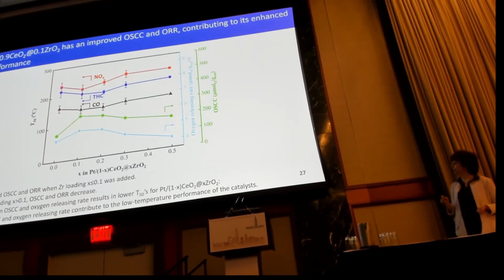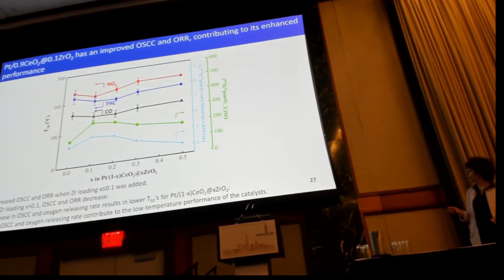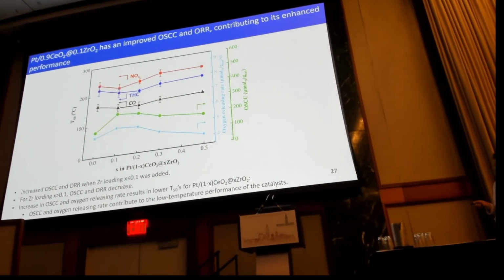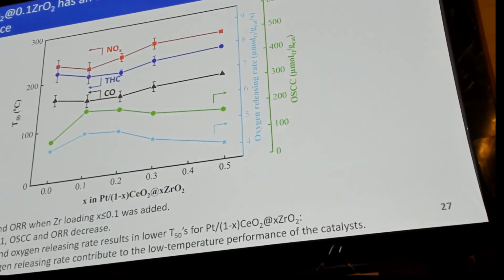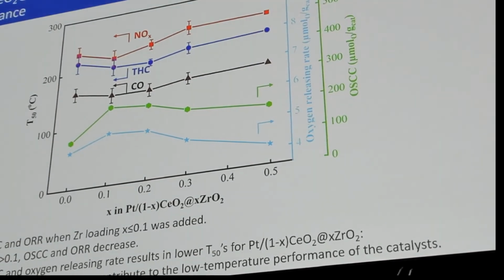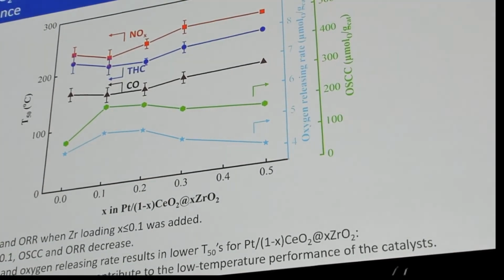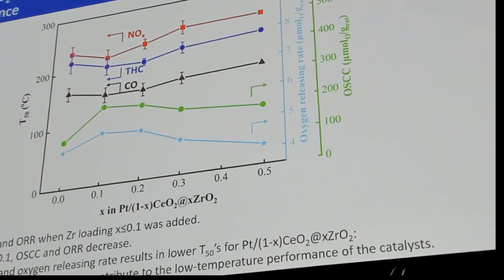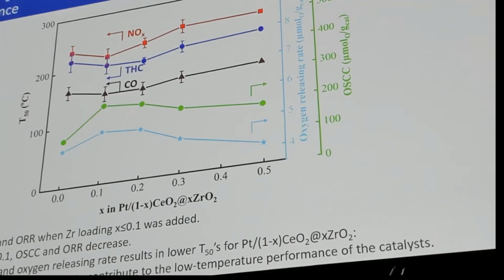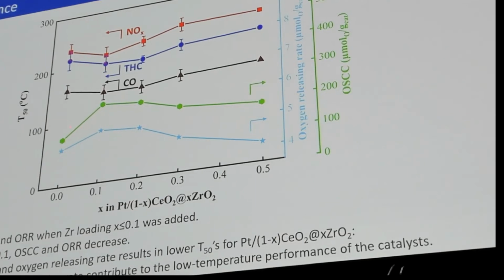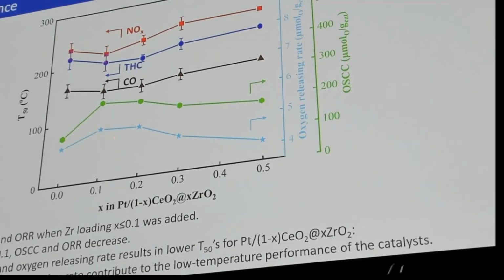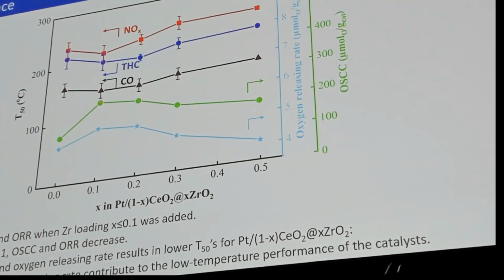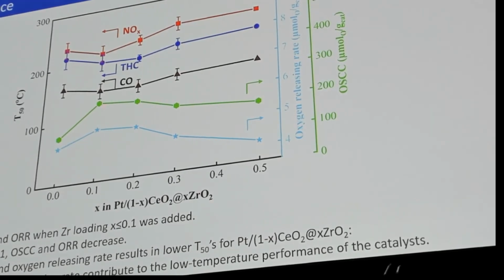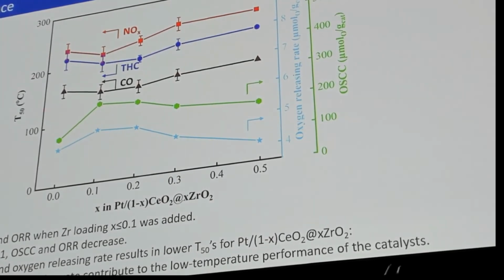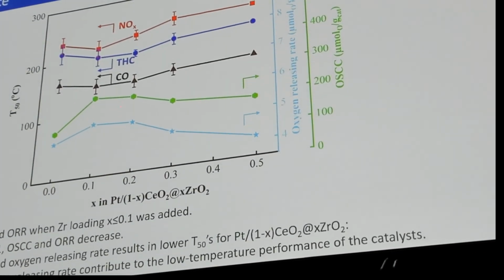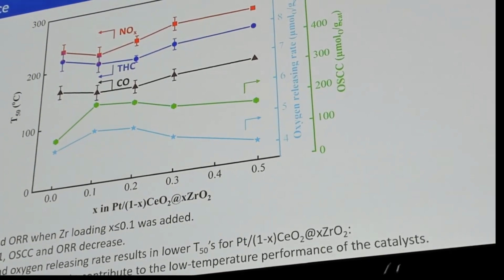So let me show you now the results. Again, the x-axis shows our catalysts, and from left to right, the zirconium content is increased. The light blue line here is the oxygen releasing rate, and we can see that it goes to a maximum when the zirconium concentration is around 0.1. And then the green line is the oxygen storage capacity, and we see again that the oxygen storage capacity goes to a maximum when the zirconium content is around 0.1.